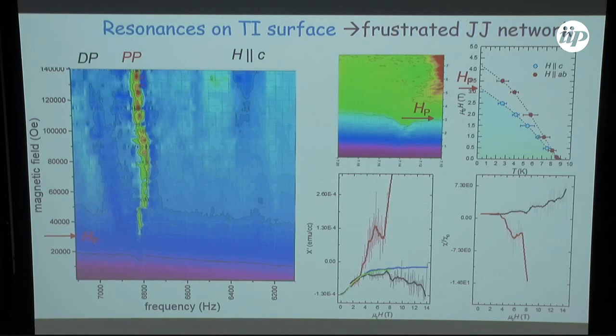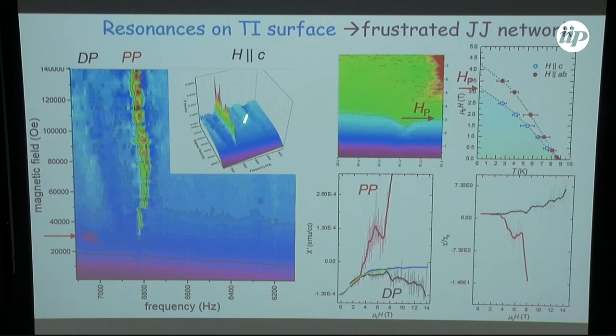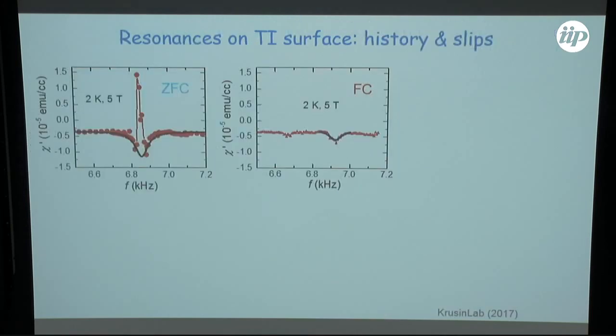And so this is actually quite remarkable. Now, this is sort of the same data. Now, you see its amplitude here of chi prime, I just showed it in projection. So you see this diamagnetic trough, paramagnetic peak, and there is another diamagnetic feature. Now, the interesting thing here is that this paramagnetic peak sits in this diamagnetic trough as well, and it is only seen in zero field cooling.